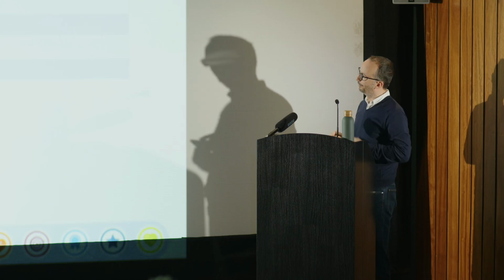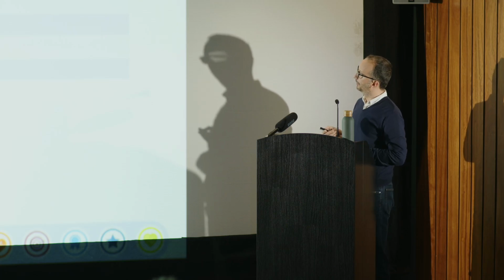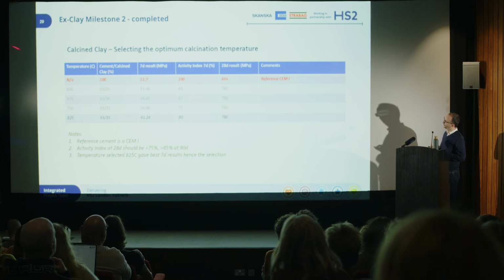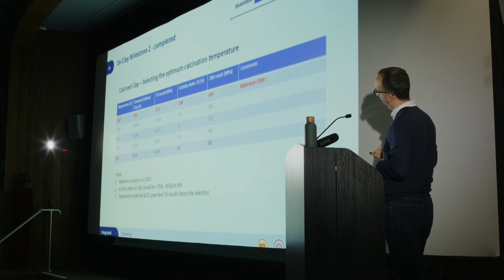Now, one question that we get a lot is how do you decide which temperature you need? One of them is the activation energy. So what we do is we basically take a reference Portland cement. This is 95% clinker and 5% limestone and gypsum. And we compare it with the strength data. So this one has only the 7-day test results, but you can see we get that as 100%. And we start calcining clay in a small kiln in the lab, and we start testing to see when we get the optimum reactivity. And for us, in this instance, it was 825 degrees. So we just went on with 825 degrees to optimize the reactivity of the clay.